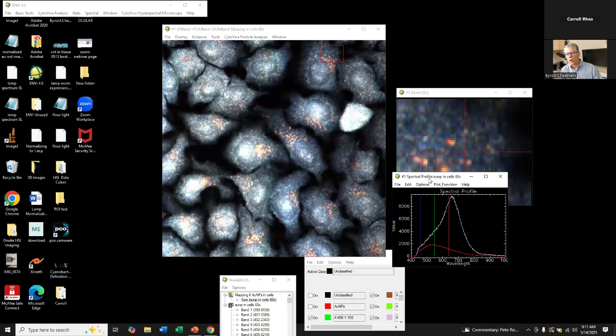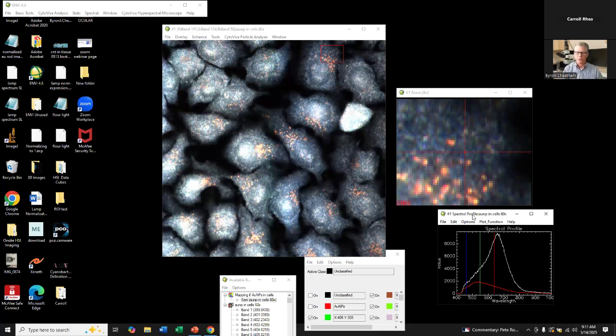So based on this information from this dark field hyperspectral image of gold nanoparticles in HeLa cells, we're able to determine that gold particles are present. We're able to get information about where the gold particles are in the cells and the relative amount of gold particles that may be present in the cell in this sample image versus other sample images where you may be using different concentrations of gold, targeting proteins, or different exposure timeframes to measure those differences and how they're reflected in the uptake.